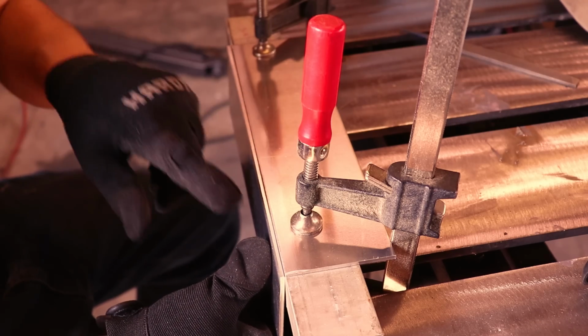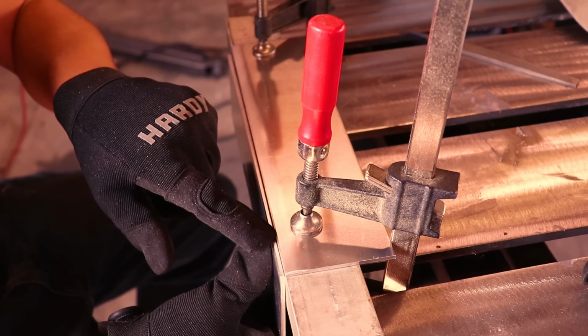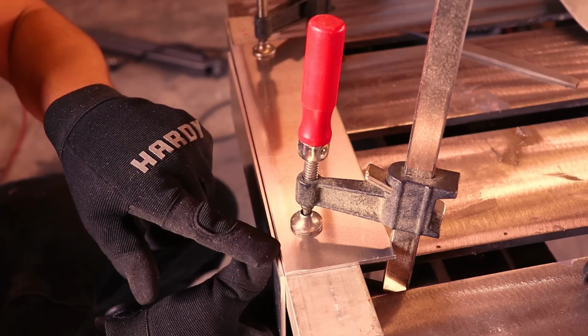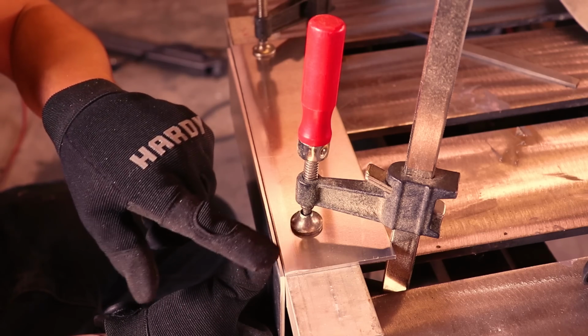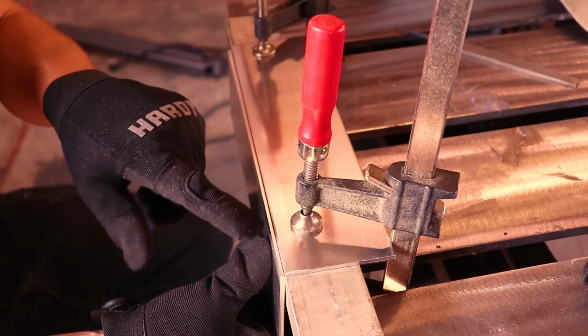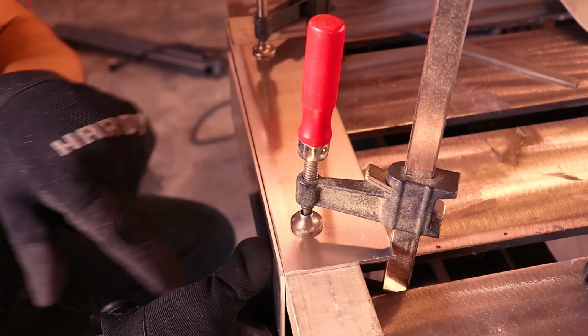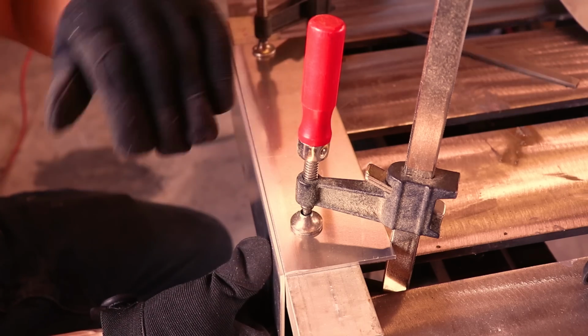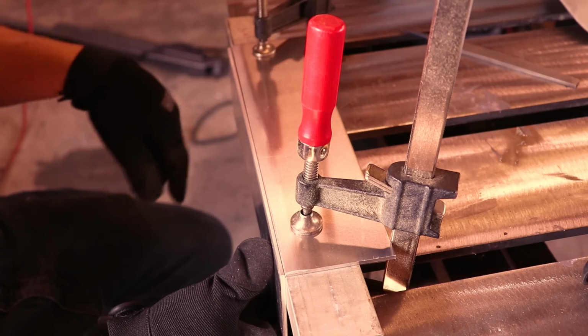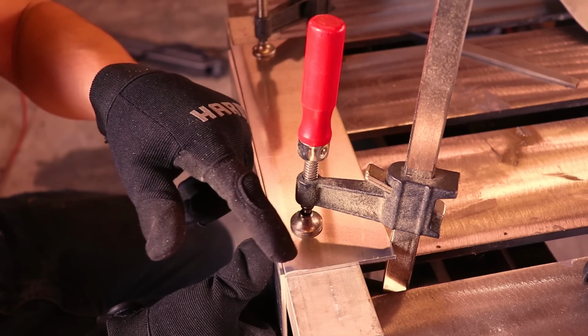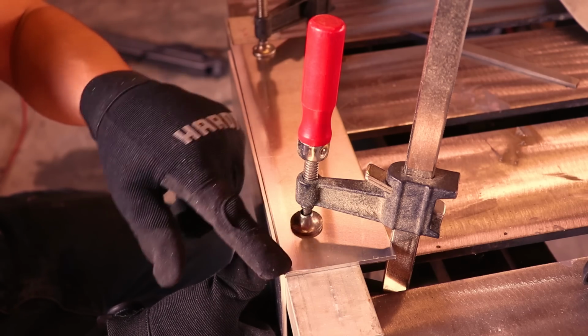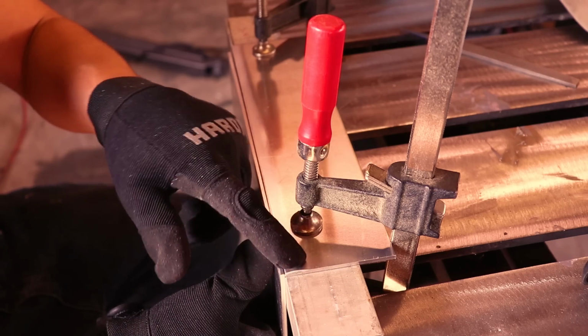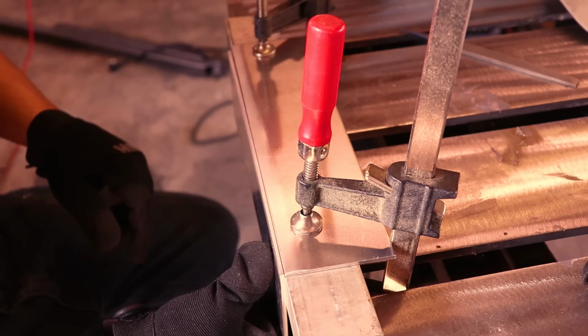And you want this valley right here when you're welding, especially aluminum, because it uses all that to strengthen up the weld, and then you don't have to use as much heat. It can cut in there and it's not going to be as high humped. If you have it like this, you're not getting much strength, and if you want full penetration, it's going to need a lot of heat, and then it's going to have a really high crown on it.